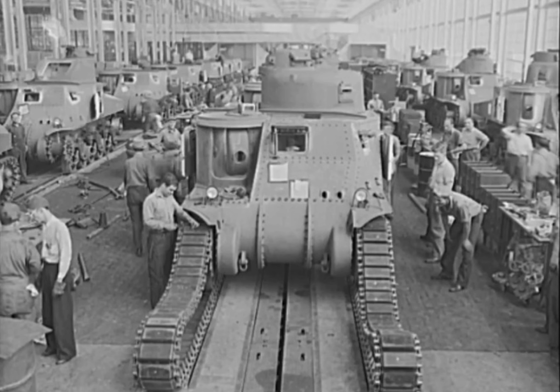After rolling to final thickness, plates underwent heat treatment, the critical step that determined armor performance. Plates were heated to approximately 1,500 degrees Fahrenheit and held at that temperature long enough to ensure uniform heating throughout the thickness. Then they were quenched, plunged into enormous tanks of oil that cooled the steel rapidly. This rapid cooling locked the steel's crystalline structure in a hard, strong configuration, but quenched steel was also brittle. The final step, tempering, involved reheating the plate to approximately 800 degrees Fahrenheit and holding it there for several hours. This relieved internal stresses while maintaining most of the strength gained during quenching. The resulting armor had optimal balance between hardness and toughness.